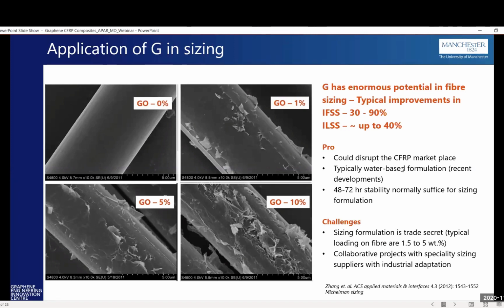But in the recent developments, sizing formulations are typically water-based. So graphene oxide-based sizing material seems to be widely studied, and it's very stable as well. One note that we got from the sizing industry is that the sizing itself, for commercial application, doesn't need to stay stable for quite a long period of time. A 72-hour stability is more than enough, because that is the time it takes for the sizing to be produced and applied onto, for example, glass fiber itself. So if the graphene-based sizing formulation is stable for 3 days, that could be enough.